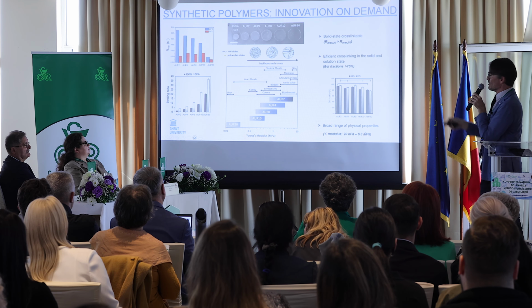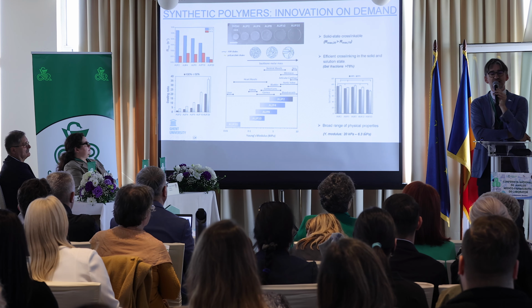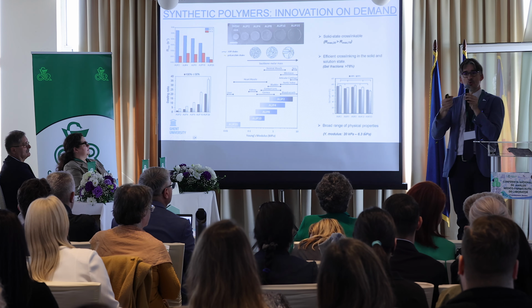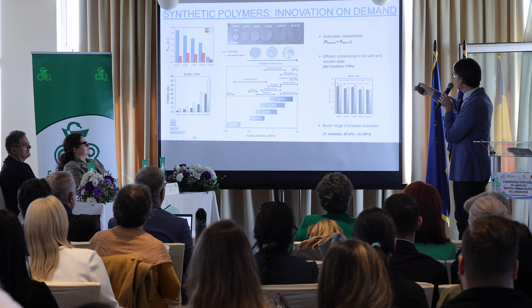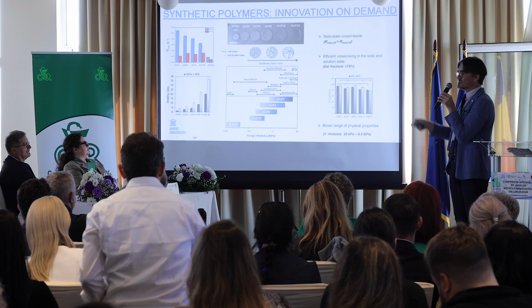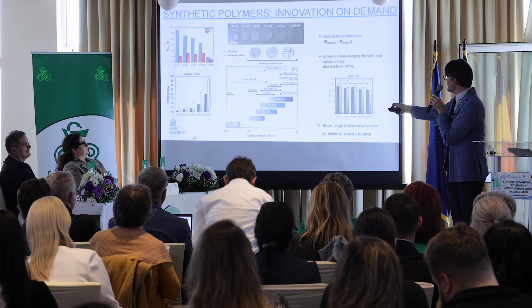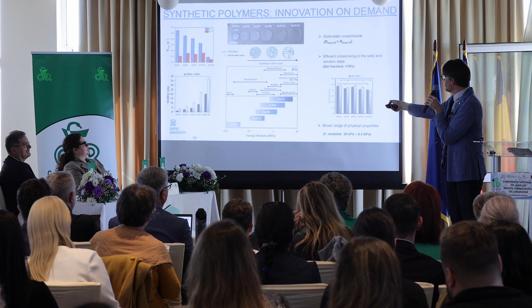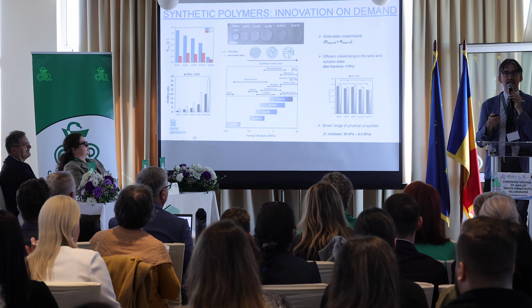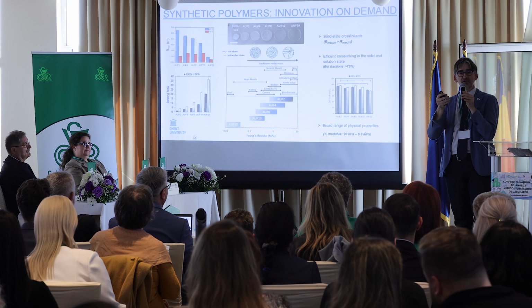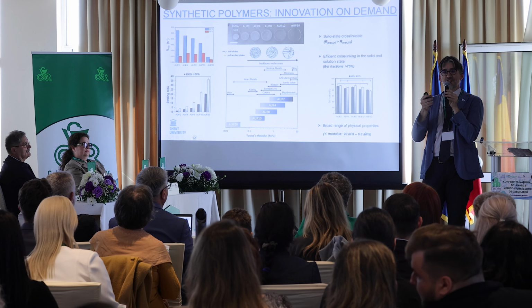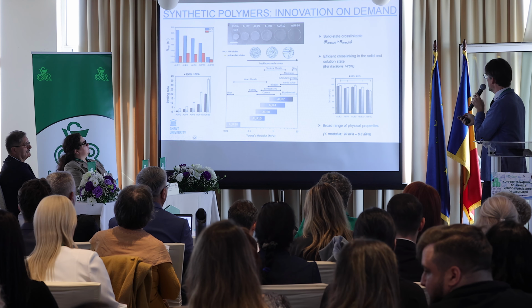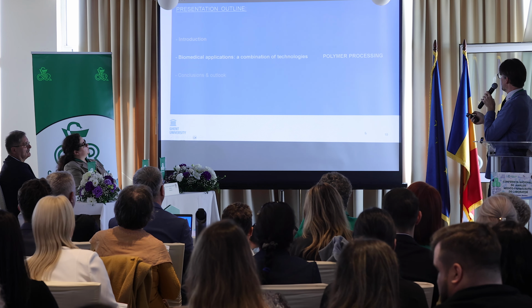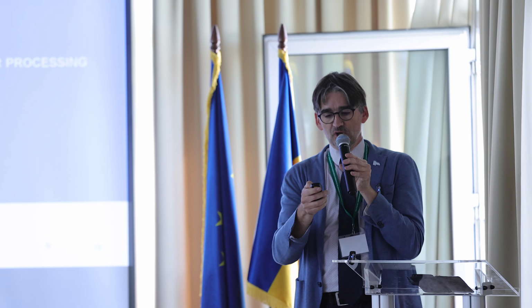And again, here a couple of other analysis techniques that were performed to study how well those materials cross-link into gels, how the swelling is affected by the molar mass. Typically, with a higher molar mass polymer, you obtain a higher swelling of the material. So a technology that enables us to carefully fine-tune the final mechanical and other properties. Good, that's the polymer technology.